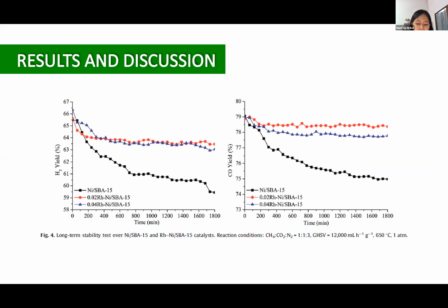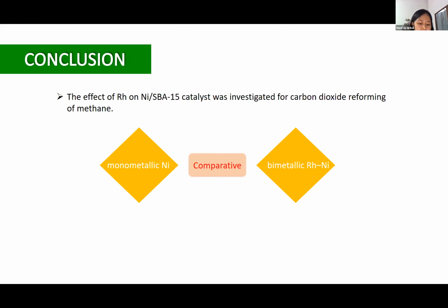Next, the conclusion. The effect of rhodium on nickel SBA-15 catalyst was investigated for carbon dioxide reforming of methane. A comparative study between supported monometallic nickel and bimetallic rhodium-nickel catalyst shows that the high catalytic performance of the rhodium-promoted nickel catalyst arises from the interaction between nickel and rhodium in the bimetallic system, which provides higher metal dispersion and improved reducibility of nickel and coke resistance.